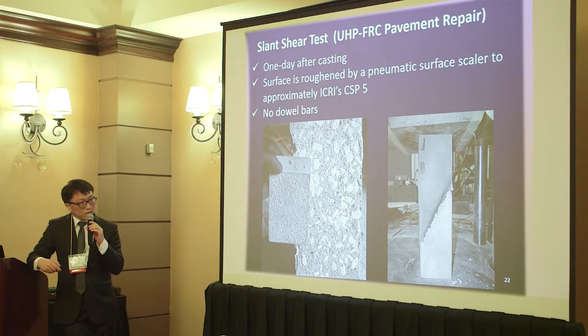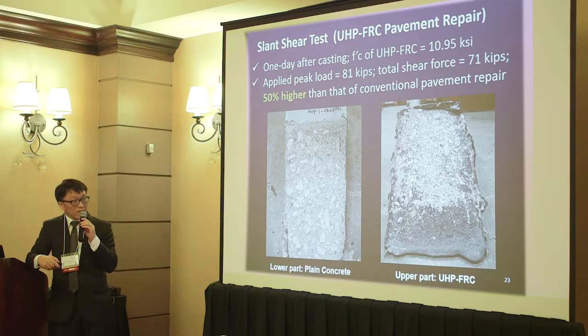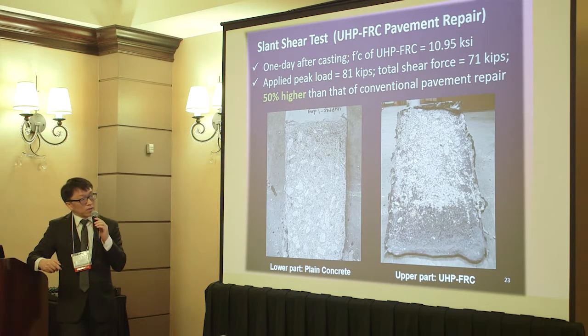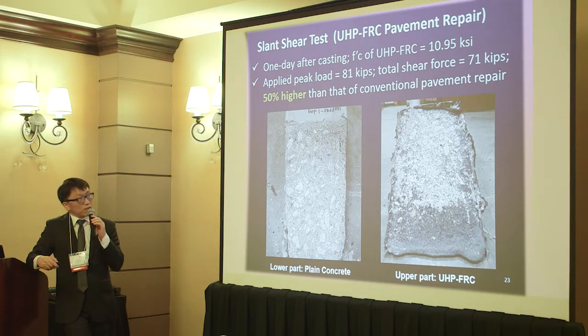In the second test, we don't use a dowel bar here, and we roughen the surface using a pneumatic surface scaler, roughly to the CSP 5 profile provided by the International Concrete Repair Institute. So the surface is roughened, with no dowel bars, and then we cast UHP-FRC on top. After 1 day, we test the specimen. First, the concrete strength reached 11 ksi, which is commonly reached for UHP-FRC.